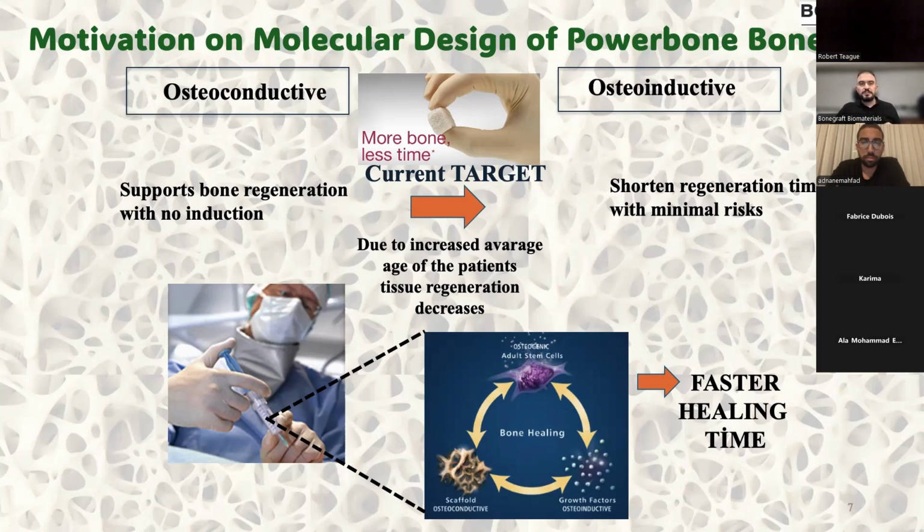During the bone regeneration period, which is conducted in 6 to 9 months maximum, the degradation molecules of beta-TCP, which are calcium phosphate ions, are being used by the bone-making cells, mesenchymal stem cells, while they mineralize the bone tissue. So basically, the graft's resorption molecules are also being used by the cells that try to regenerate the bone tissue.